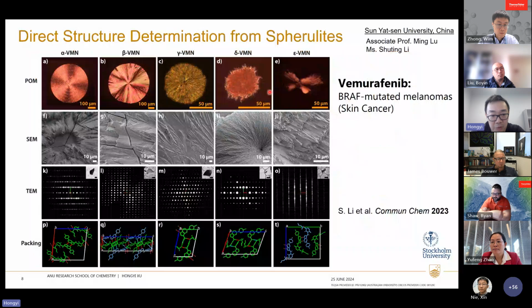So what we do with MicroED is crush these spherulites and end up with small fragments, and often these small fragments are single crystals. By using MicroED, very straightforwardly, we can collect very nice data from these small fragments of these beautiful spherulites, solve structures, and treat them as if they are single crystals. So it's very straightforward for polymorph discovery. It's actually very useful. It will speed up the process by which a polymorph can be discovered.